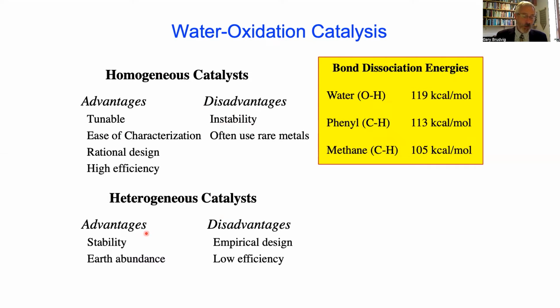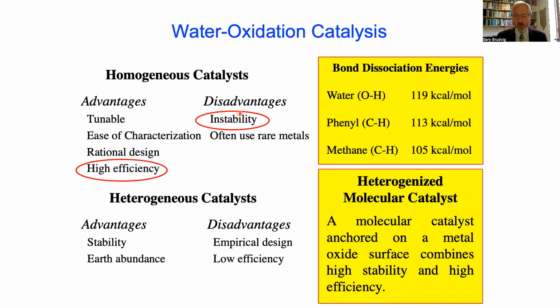On the other hand, heterogeneous catalysts, such as metal oxides, can be much more stable. But the drawback is that they often have low catalytic efficiency, and the design is often empirical. So what I'll describe today is how we can maintain the high efficiency of a molecular catalyst, but overcome the instability by attaching it to a surface, so heterogenizing the molecular catalyst by using anchoring chemistry to attach it to an oxide surface, which then combines very high stability and also high efficiency.